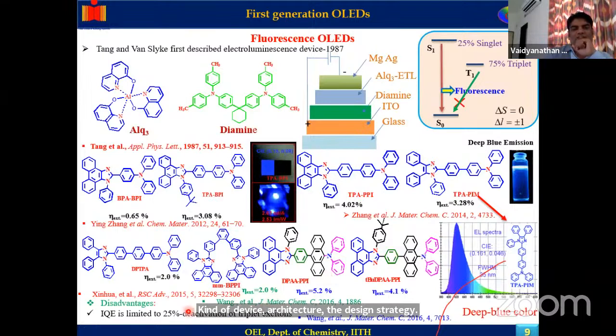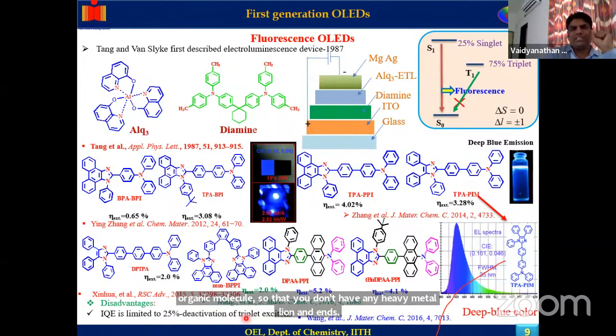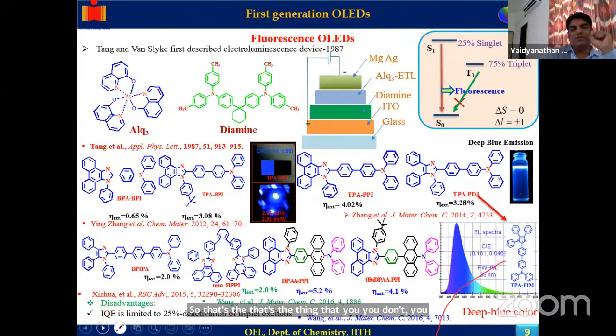The only disadvantage is that the internal quantum efficiency is limited to 25%. Deactivation of the triplet exciton is not possible with a simple organic molecule, so you don't have any heavy metal ion, and hence one cannot harvest the 75% of the triplet state to the ground state. So you don't consider this an efficient material.